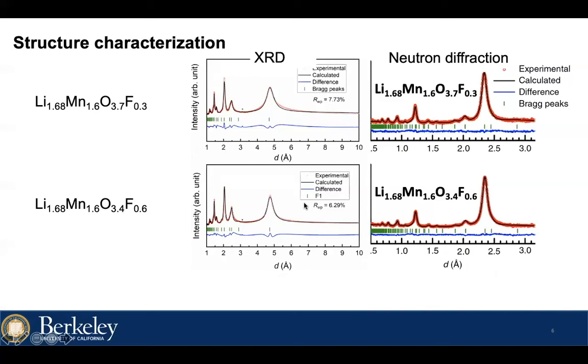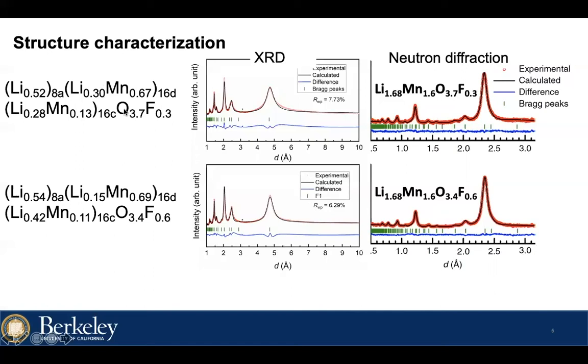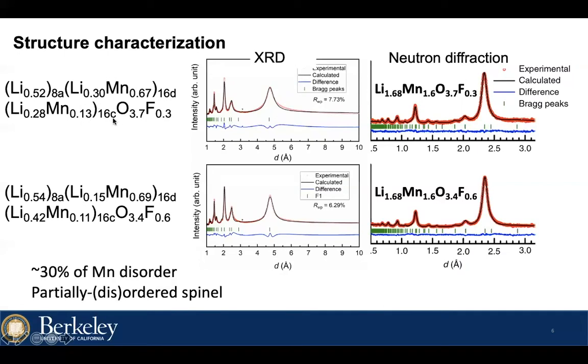Combining the refinement of the diffraction data, we can get the site occupancy in such a spinel-like structure here. Recall that in the ordered structure, all the manganese are in the 16d site, leaving the 16c site vacant. However, in these two materials, part of the manganese is distributed in the 16c site. That means around 30% of the manganese is disordered. So we will call this kind of material a partially disordered spinel.